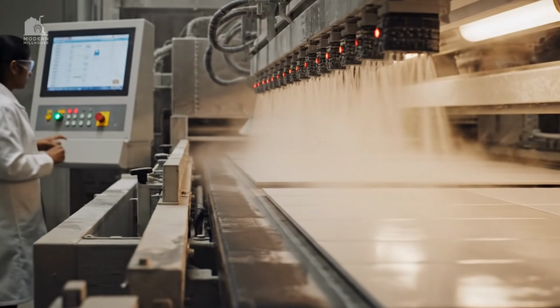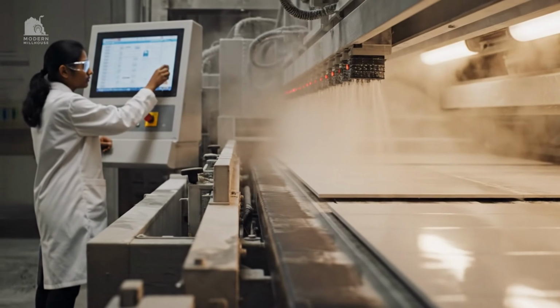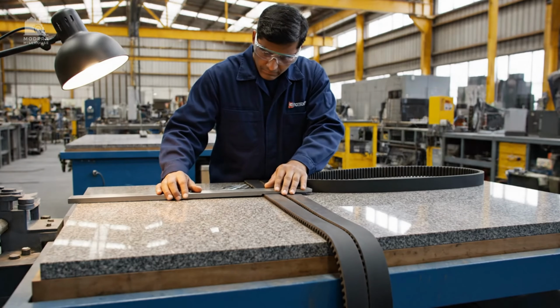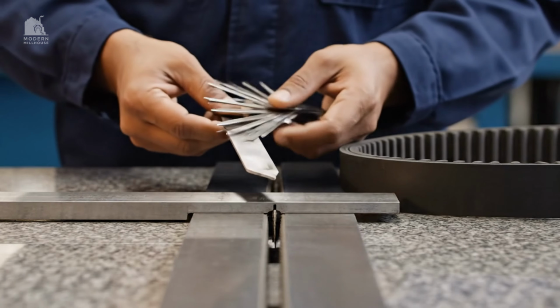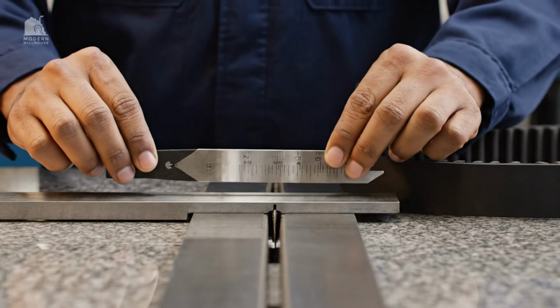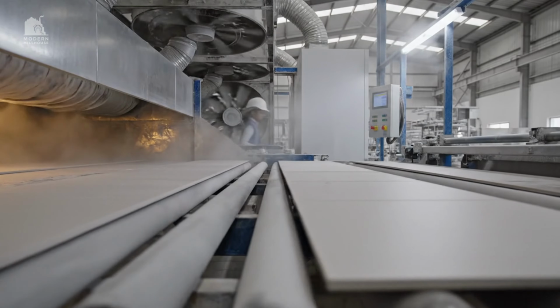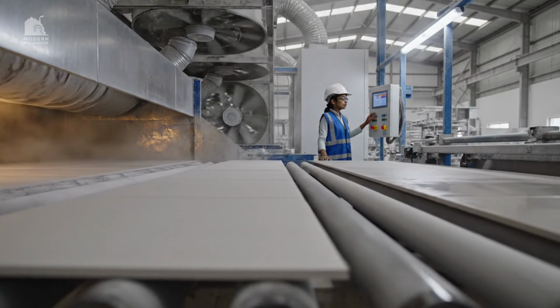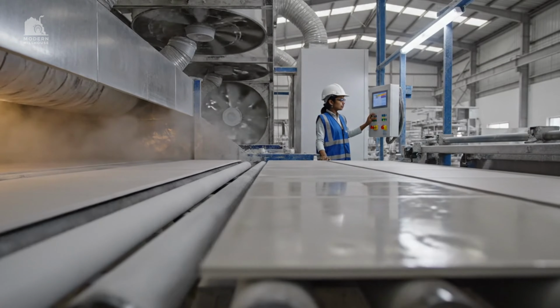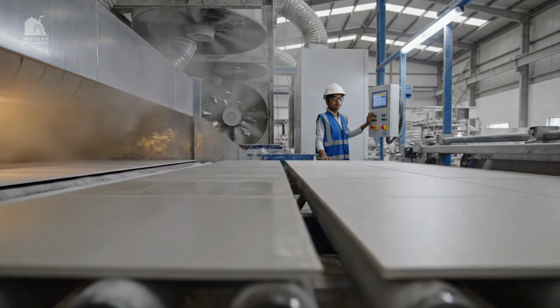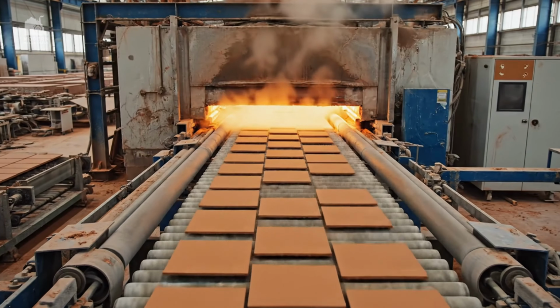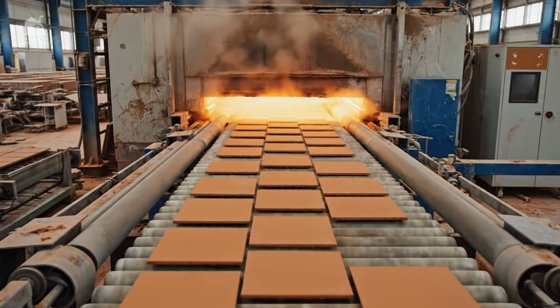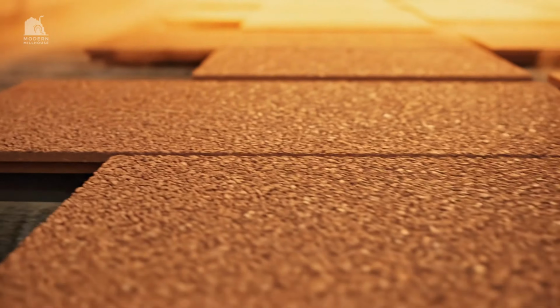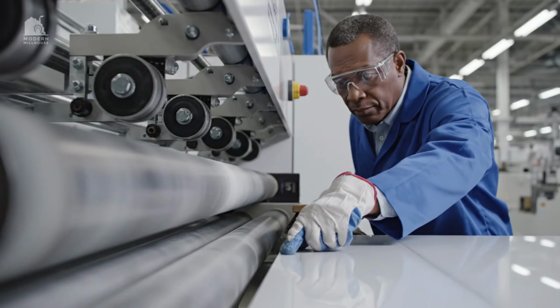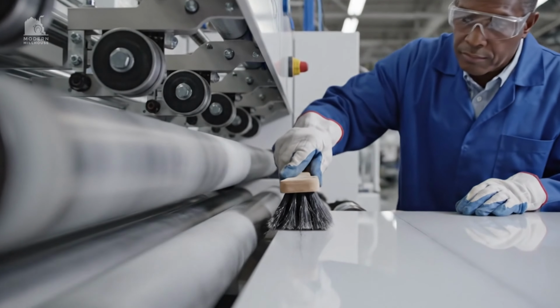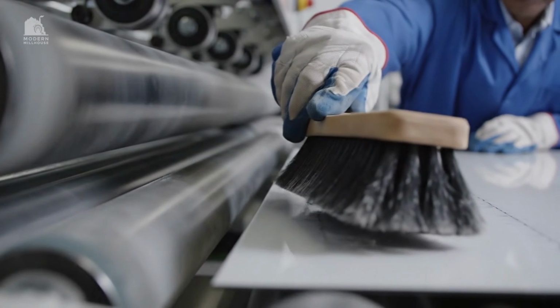Sensors track temperature and moisture so operators can adjust in real time. Dryer belts and rollers must stay clean because debris can imprint the underside and create stress points. Plants control tile exit temperature so glaze does not flash dry on contact and trap bubbles. After drying, tiles are flatter, lighter, and strong enough for glazing lines. Some products get light brushing or edge cleaning to remove dust and improve adhesion.